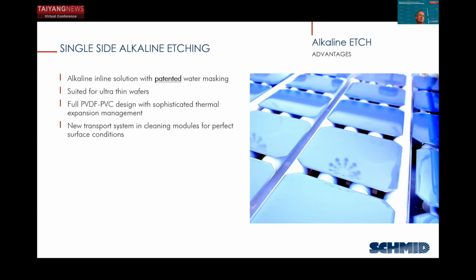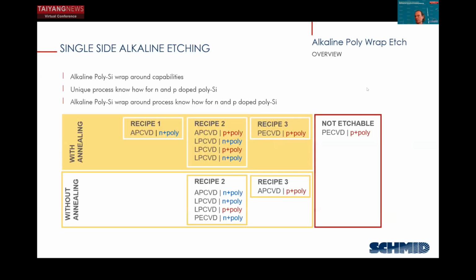It's a full texturing PVDF and PVC, PP design with a sophisticated thermal expansion management and a new transportation system, which we have invented to provide a perfectly cleaned surface. Also very important for us to mention is that depending on what kind of system and doping you use in your polysilicon process, you may have to use a slightly different process recipe. We've run through our systems all sorts of different combinations done with the APCVD, LPCVD, PECVD systems. And we found that most of the dope glasses or polysilicon stacks we can remove. What we've seen is very difficult is a PECVD P+ poly, which is very difficult to etch.